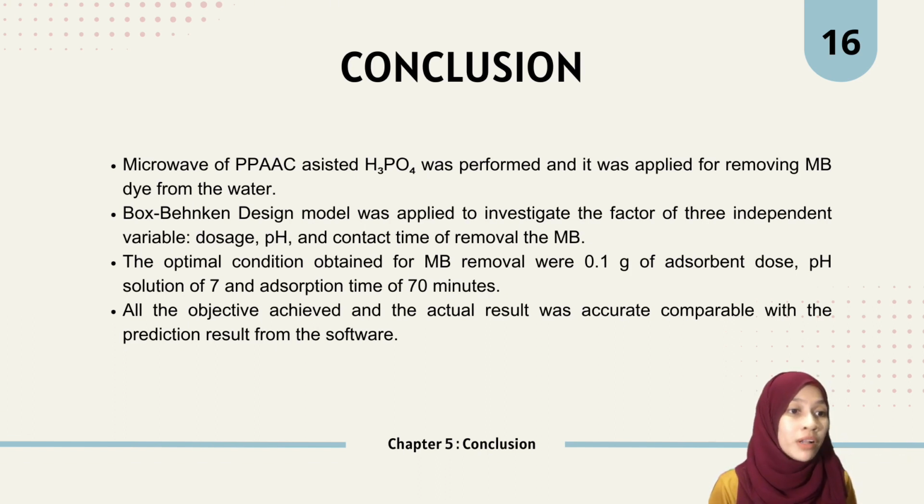Number 3, the optimal conditions obtained for methylene blue removal were 0.1 gram of adsorbent dose, a solution pH of 7, and an absorption time of 70 minutes. Number 4, all the objectives were achieved and the actual result was accurate, comparable with the prediction result from the software.